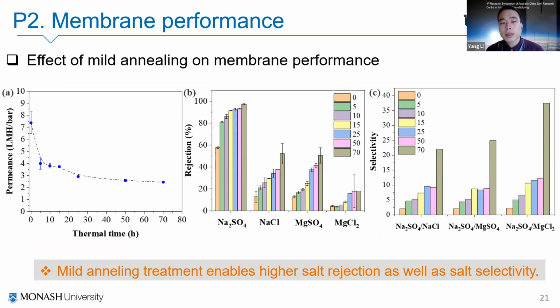However, we get to know the salt separation is increased when we prolong the thermal treatment time, and the salt selectivity between the sodium sulfate and some other ions is increased with time as well. So the mild annealing can enable tunable salt separation as well as a higher salt selectivity.